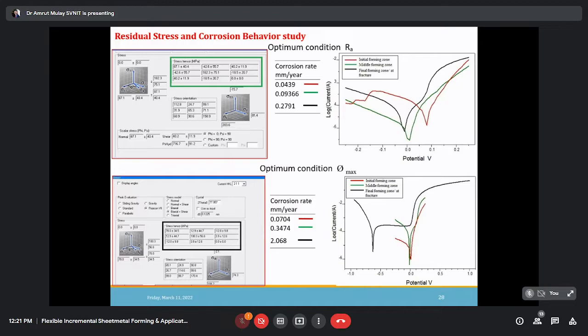So corrosion resistance is very poor if the material is stressed. Corrosion resistance is very poor when the material is loaded, means corrosion will be high in case residual stress is high. Mm per year, it means that 0.2791 mm per year. Always it is in per year.